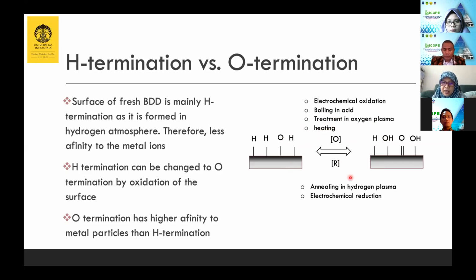And can we change this oxidized diamond back to normal diamond, or hydrogen terminated diamond? Yes, we can anneal in hydrogen plasma. We put it again inside the CVD machine, give hydrogen plasma, and it will be hydrogen terminated again. We can also do electrochemical reduction by stepping to a very negative potential. It will change some oxygen termination to hydrogen termination.